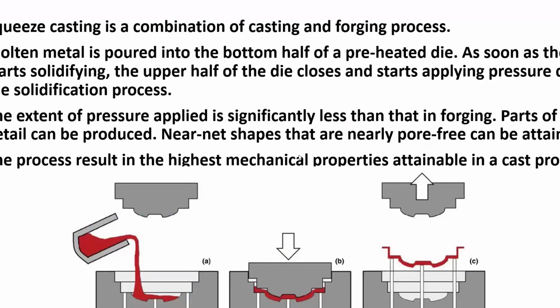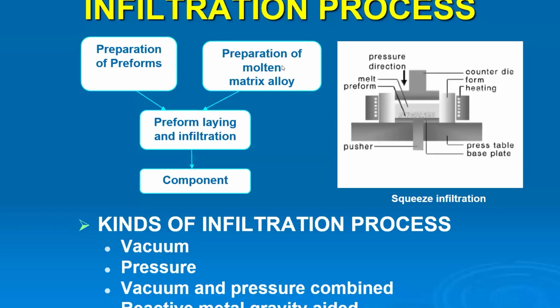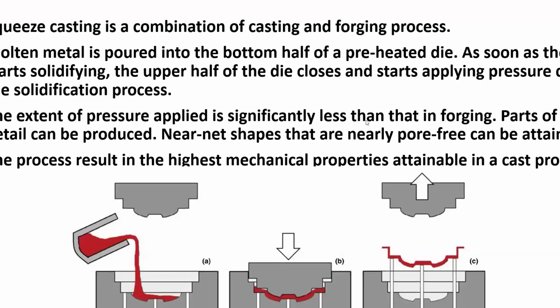So this squeeze casting process is a combination of casting and forging. In high pressure die casting, when you pour the metal in, the plunger comes and hits and it gets filled. But here in squeeze casting, we apply the pressure until solidification happens, and the components will be of very high strength. That means the highest mechanical properties are achieved in the cast product, and these are near net shape with nearly zero porosity. This is the concept we use to make infiltrated products also.